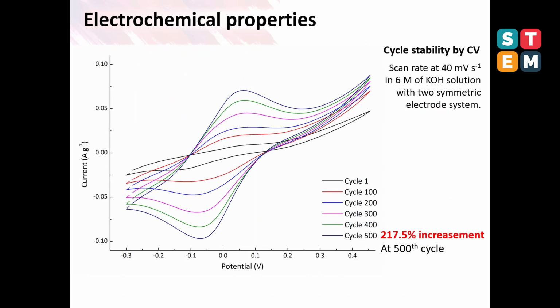When investigating efficiency over long cycling, the area of the CV curve increased with long use. The results show the activation of the material. At 500 cycles, the specific capacitance increased to 217.5%. That means this material can improve its performance the longer it is activated.